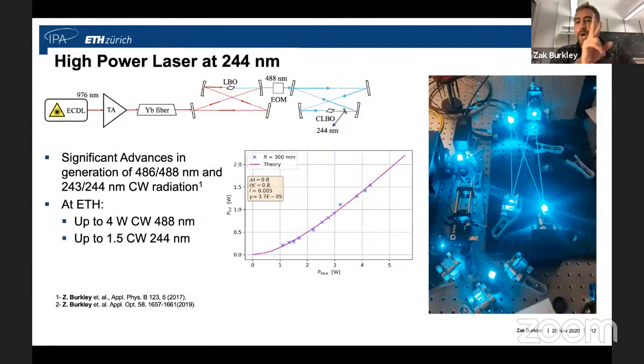And I'd like to talk to you now about requirement number 2, this high power laser at 244 nanometers. How this laser operates is it starts in the infrared with an extended cavity diode laser at 976 nanometers. It's then amplified twice through a tapered amplifier and a ytterbium fiber amplifier. And this ytterbium fiber amplifier is very key as it gives us a high amount of 976 such that we can generate a lot of power in these doubling cavities. We go to 488 and then we go to 244. And thanks to some significant advances in the generation of this high power UV light, we are able to get up to 1.5 watts of power at 244 nanometers.